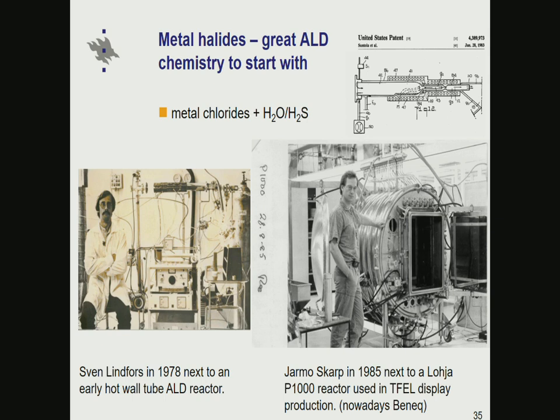When Suntola and his co-workers started ALD in Finland, they were very lucky to choose metal chlorides as the first precursors, for the reason that there were hardly too many alternatives, and these were again the cheapest ones to start with. They started using metal chlorides with water and hydrogen sulfide in depositing oxides and sulfides. Motivation was coming from these electroluminescent displays.